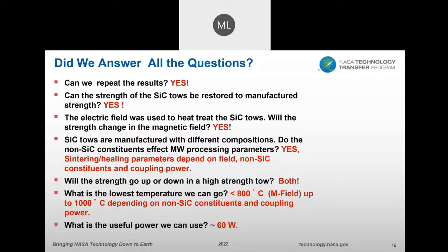Somewhere below 800 degrees. We really have to do some more studies to actually measure that temperature. And the lowest temperature that we had good results in the electric field was 1000 degrees, depending on the non-SiC constituents and the coupling power of the fiber tow. And what was the useful power we used? It was approximately 60 watts. Next slide, please.